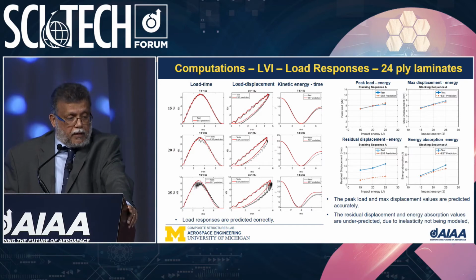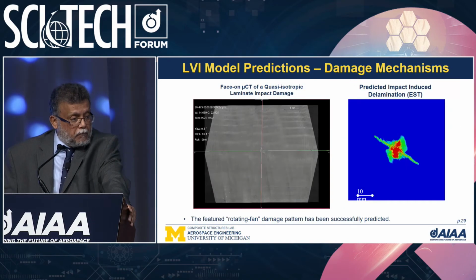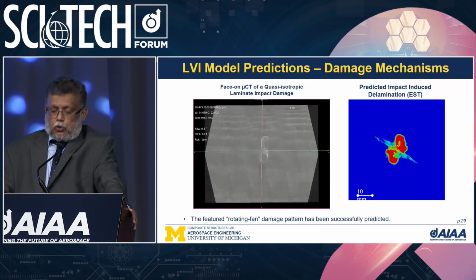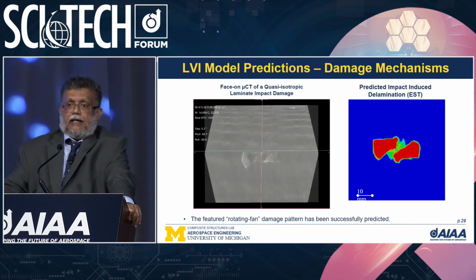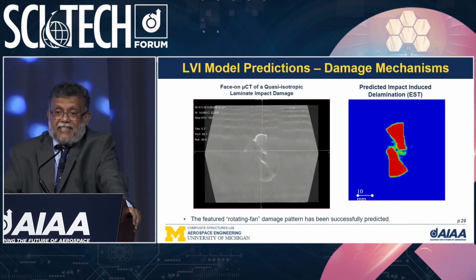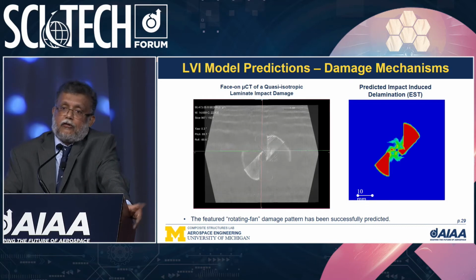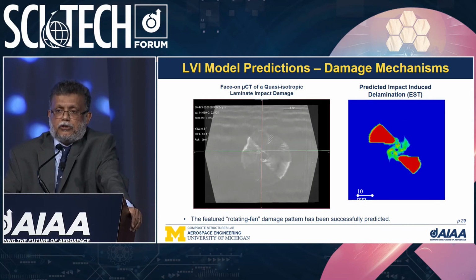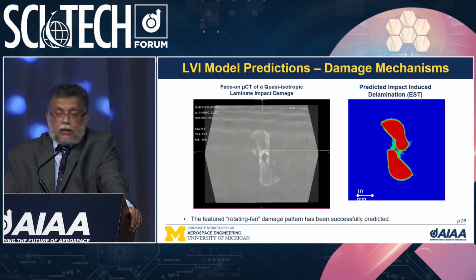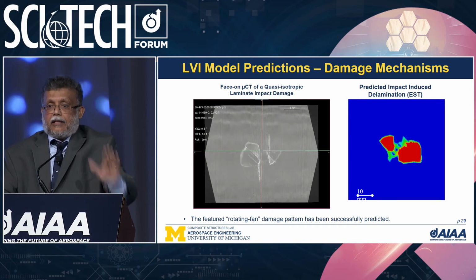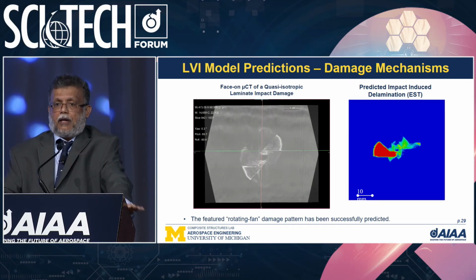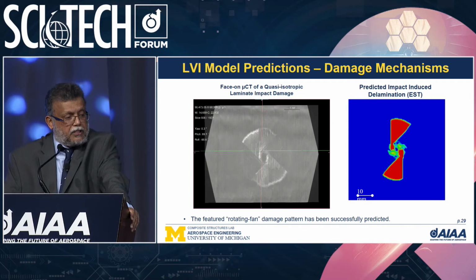These are for 24-ply laminates. Now here's a movie that shows on the right-hand side the impact damage predicted by the EST tool, and on the left-hand side a high-resolution micro-CT image going from the top of the laminate into the interior, showing ply by ply what happens to the delamination areas.